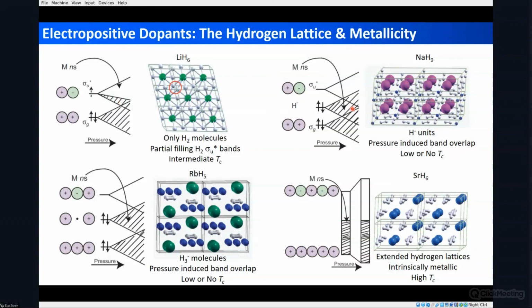Another chemical motif that we have seen in a number of the high pressure hydrides is where you have H- units that are formed, such as in this NaH9 compound. And in this case, the sodium donates electrons to this H-, and one would have an insulator at 1 atmosphere. If you put pressure on the system, you end up getting this band broadening and eventual overlap. However, the density of states at the Fermi level is not high in these systems, and the metallization pressure is usually underestimated with the standard PBE gradient functional.